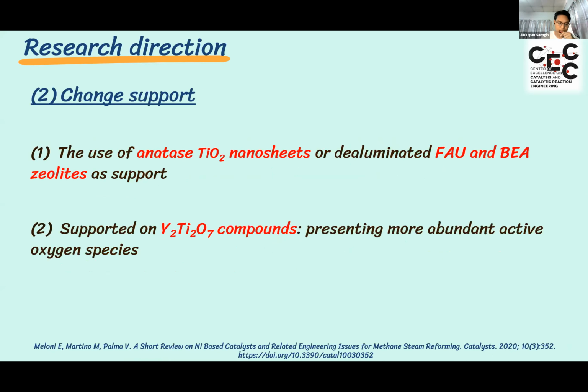And the other method is changing the support. For example, use anatase titanium dioxide nanosheets or use dealuminated FAU and BEA zeolites as a support. Or second is to supported on V2Ti2O7 compounds, where more abundant active oxygen species are present, being beneficial to remove the carbon deposition and keeping the nickel size free from coating.